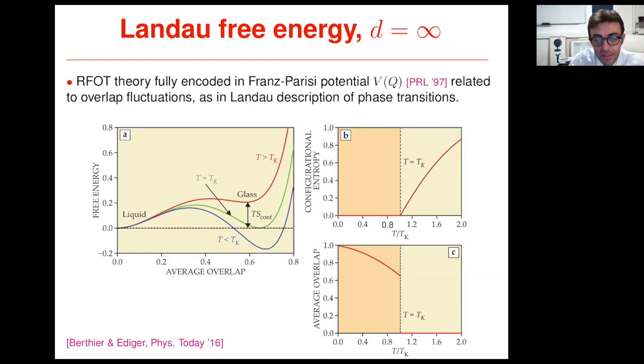And it has the behavior expected near a first order transition. So you see these two minima whose relative stability is changing as you change the temperature. So above the glass transition, the glass phase at large overlap is metastable with respect to the liquid. And both phases then have the same free energy at the Kauzmann transition Tk. And below, at low temperature, it's the glass which is the most stable state. So we can show that the free energy difference between the liquid and the glass is directly related to the configurational entropy I mentioned before.